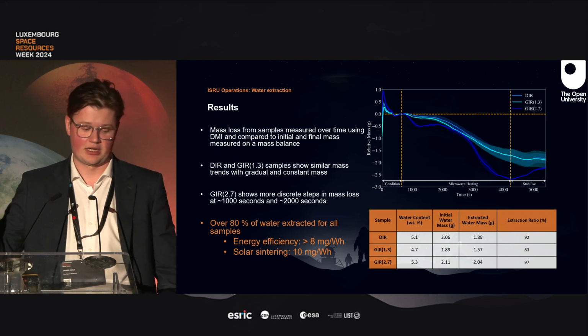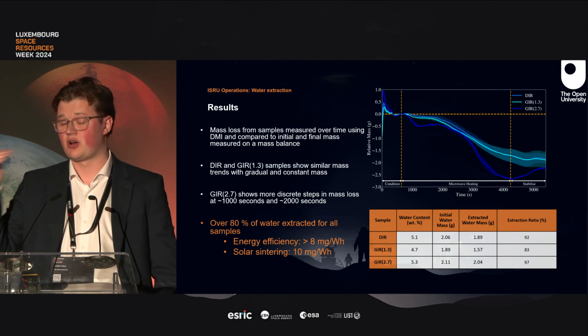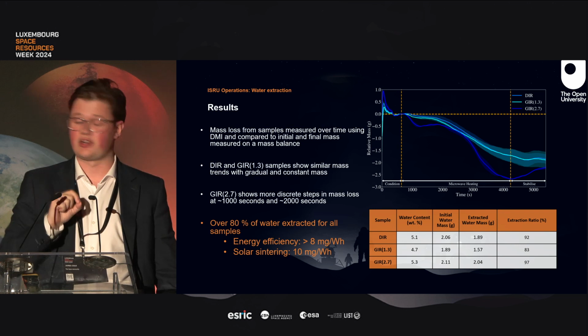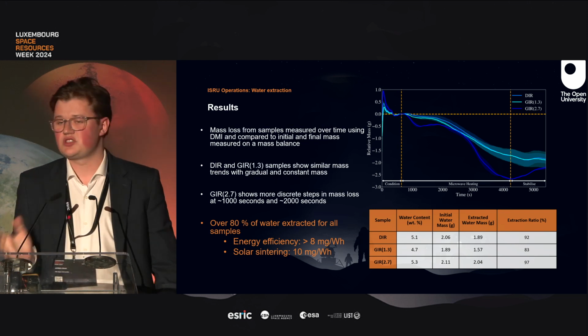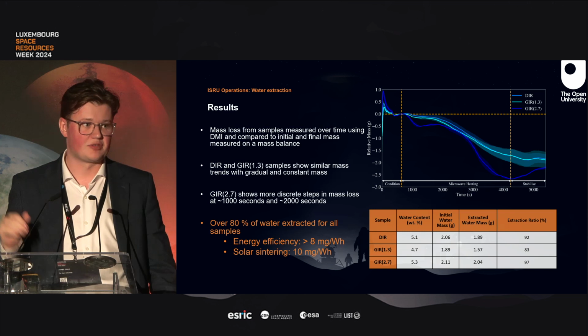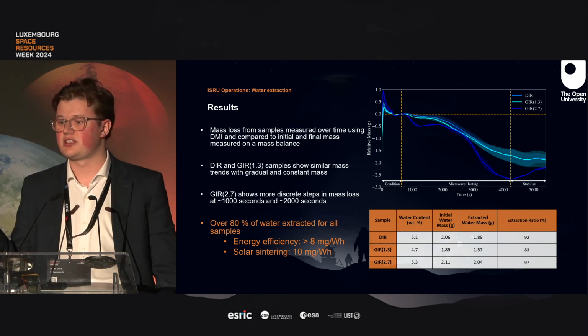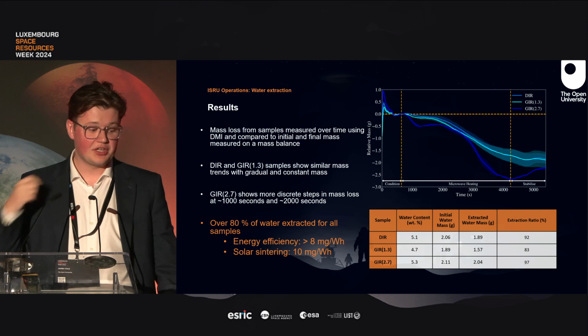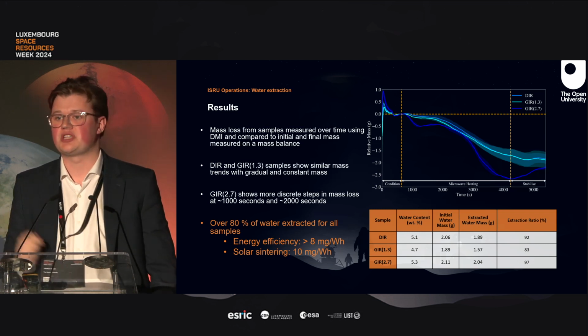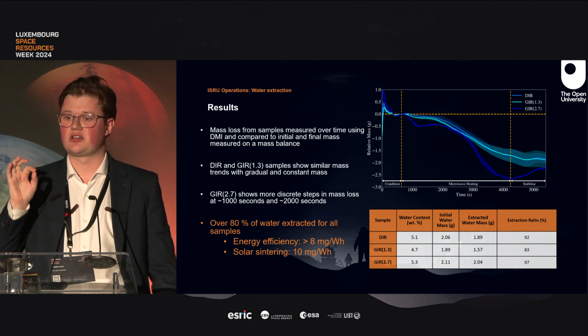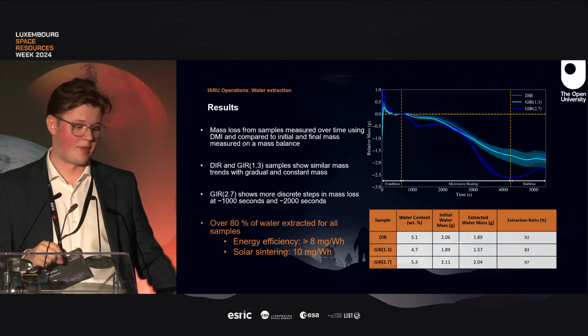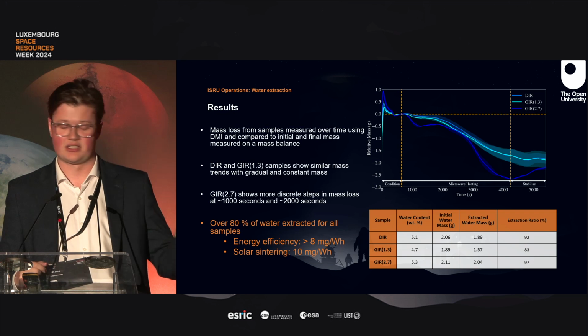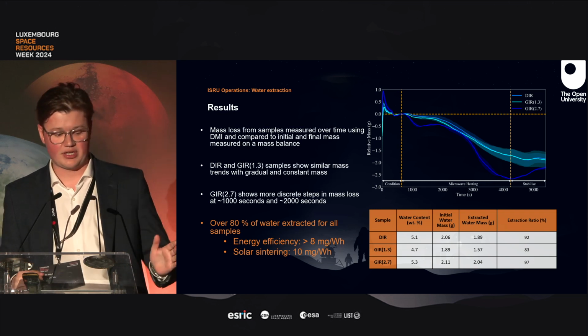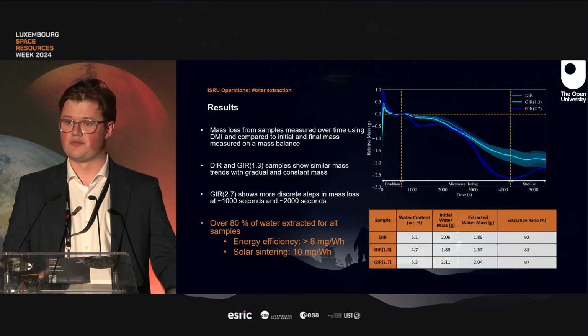And then after that, it's just a section where we leave the microwave energy off, and we just see there's no more changes to the mass occurring. The important thing to note here is that for the diffuse ice and the granular ice with smaller grains, the mass loss is fairly consistent. It starts losing mass when you turn the microwave energy on, and then it's got a nice, fairly straight line while it does so. The interesting thing is that the granular ice with the 2.7 millimeter grains, it loses ice in quite discrete sections. So about 1,000 seconds, you lose a large chunk, and then it stops losing mass. And then at about 2,000 seconds, again, a large chunk of the ice is lost fairly quickly